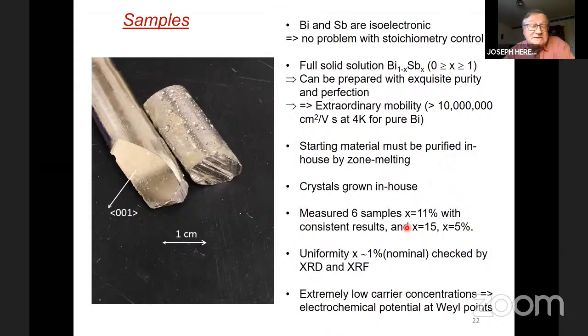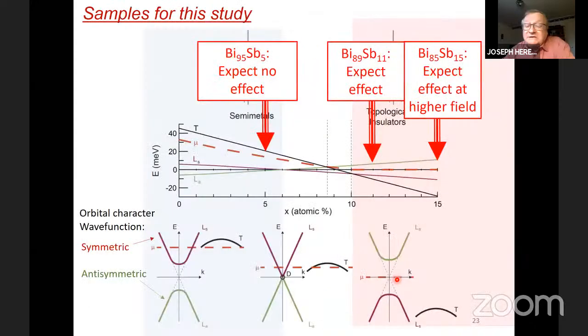We measured six samples at x is 11%, and then samples at 15 and 5%. I'll show you that in a minute. The uniformity is critical. It's nominally 1% over the whole length of the sample, which is like 5 centimeters, but over the sample that we measure, which is a millimeter cut out of the 5 centimeters, it's much better than 1%. And we have extremely low carrier concentrations. I will show you that in a minute. But first, let me show you the families of samples.